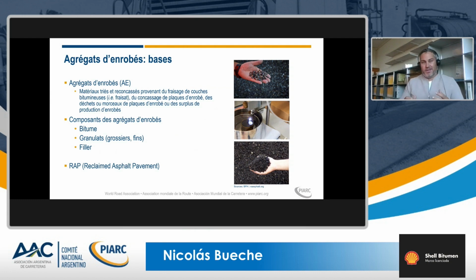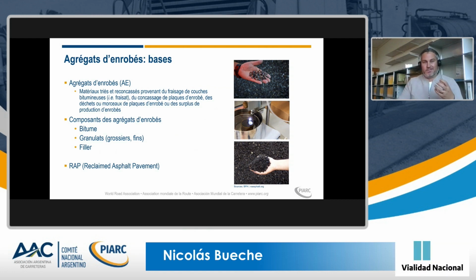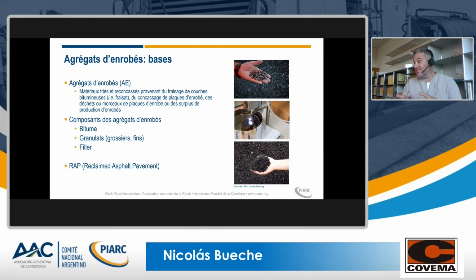For sure, it's very interesting. From a Swiss perspective, if we take a RAP, there is approximately 5% of binder, but this 5% of binder has a very high value. Talking about price, if you pay, let's say, 100 Swiss francs for 1 ton of asphalt, in our case, the bitumen will cost approximately 40%. So the value of the bitumen in this RAP is very, very important. That's why we try to reuse as much as possible. And we also call it the same as you call reclaimed asphalt pavement.